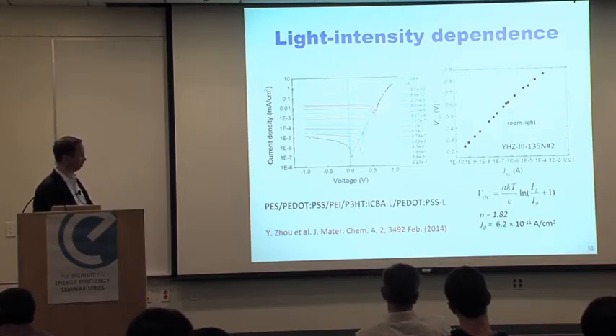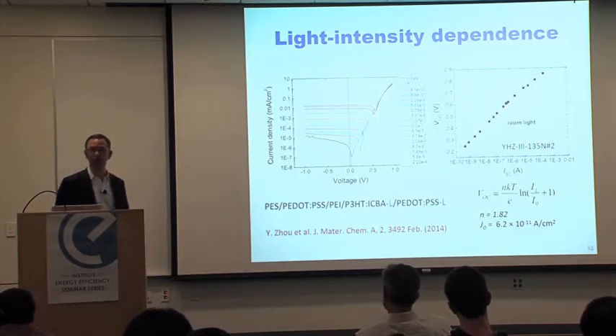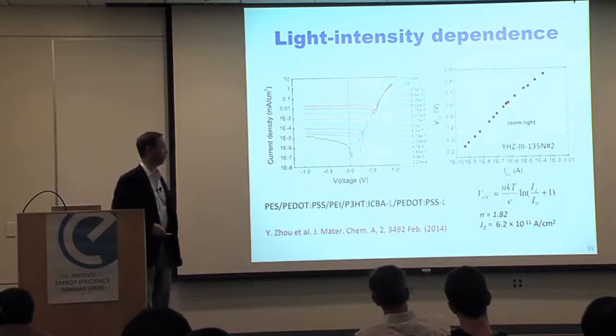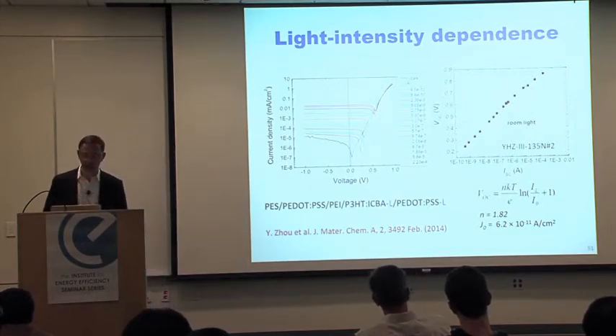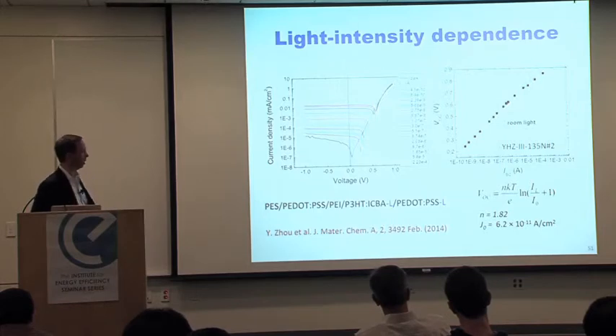And you can see that the reverse saturation current, which you can derive from the intercept of that curve here, is actually typically in the picoamp or tens of picoamps per centimeter, much lower than what one would measure in [other devices] where most of the time the current that you see is limited by shunt resistance.